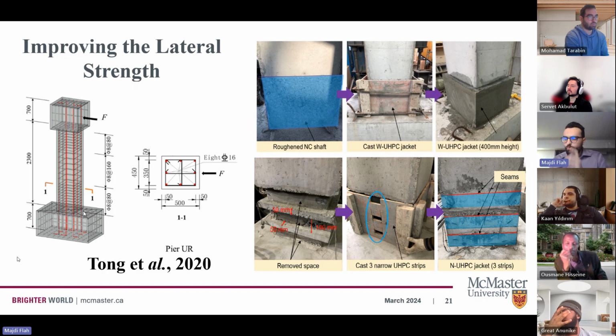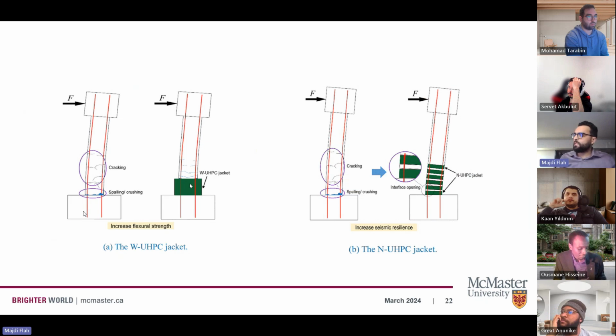So we need to think about the UHPC performance in there. This is a comparison between the two. The first one, we had some spalling and crushing in the interface between the footing and the column. When we put the UHPC jacket, you can see we don't have any problems in spalling. It's just some minor cracks along the shaft of the column. When we move to the multi-narrow strips, here it's a better behavior, less cracking.